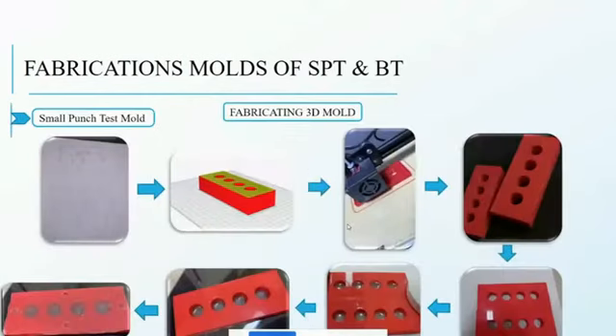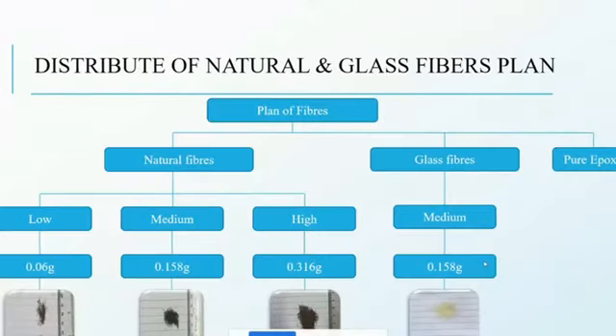For the fabrication using the 3D printing, we do the blueprint, and at the end we get the final shape that we are trying to do. We got some difficulty, some of the samples stuck due to the high roughness of the layers of the 3D printing. So we do some kind of smoothing of the surface, and at the end we get some good samples that can be used for the small punch test.